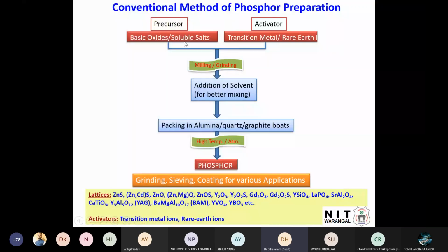And this is a simple conventional method of preparation, the solid state reaction. You take powders of oxides and activator powder, and you mill and grind them in a pestle and mortar. And if you want to mix it very well, you can add a little bit of solvent like alcohol or a little bit of acetone, and you can mix. This is only for better mixing. No need for the solvent. Dry mixing also you can do. Once you mix it, you pack it in alumina pots or a graphite boat, and with high temperature treatment in a particular atmosphere you get the phosphor. This is the conventional phosphor preparation technique.